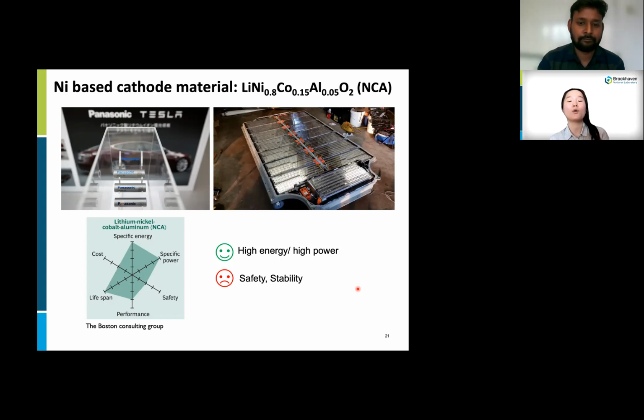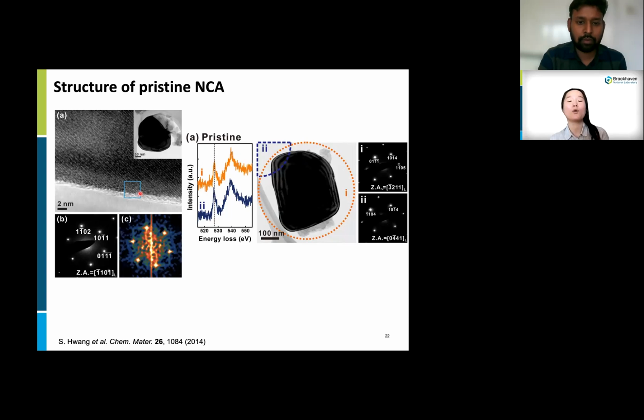To see the changes after charging, which is lithium extraction, different amounts of lithium ions were removed from the original material. Half charged means 50% of lithium ions were extracted. Overcharged means 90% of lithium ions were extracted. This image was acquired from half-charged material, and even though only 50% of lithium is used, I can see spinel or rock salt phases at the surface, which means local structural degradation happened.